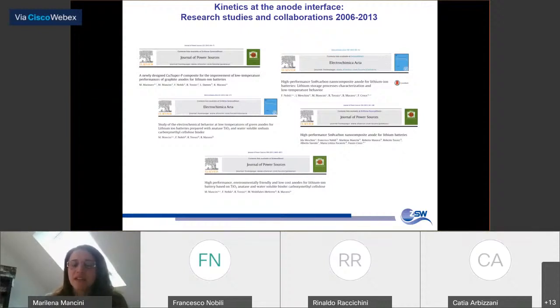And in 2009, we also started another topic in Camerino, which is related to the use of water-soluble binders for producing the anodes. And we have applied this approach successfully not only to graphite, where the use of aqueous binders is nowadays the state-of-the-art processing, but also to other systems like silicon carbon materials and titanium dioxide anodes.